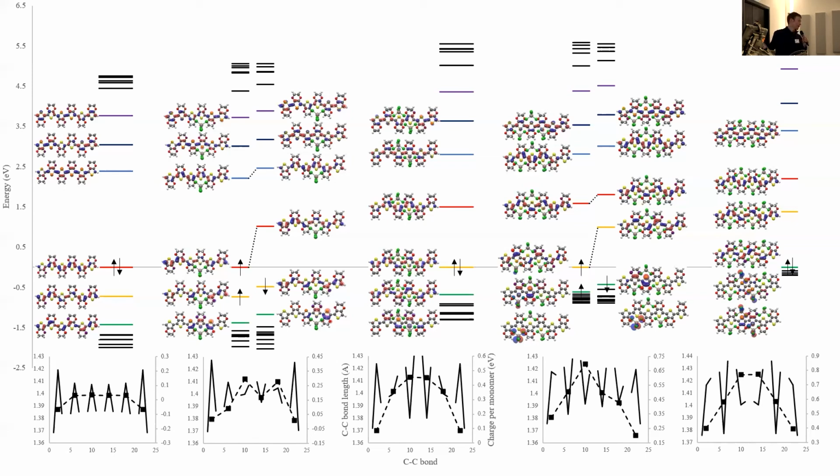Because these electrons are mobile across the system, there is a preference for the electrons to pair. So if you actually look at the system as a whole, you tend to end up with paired electrons once the system's actually reached equilibrium. It is possible to build up a spin concentration as you charge this system. So that's point number 2 against the bipolaron model.